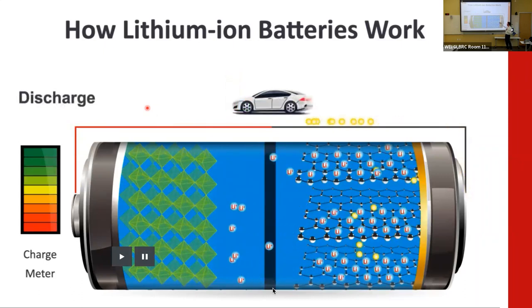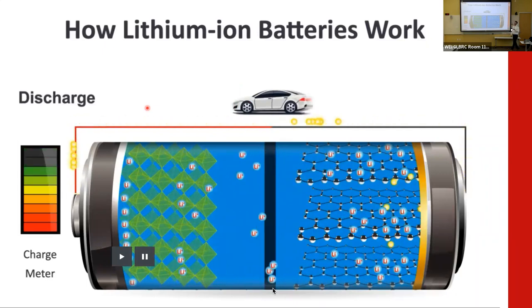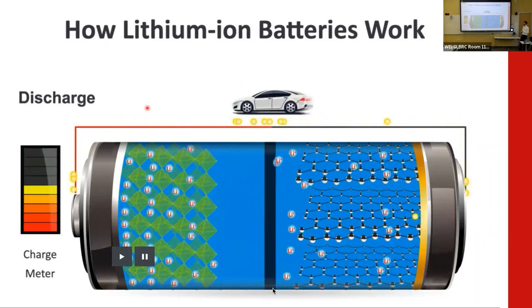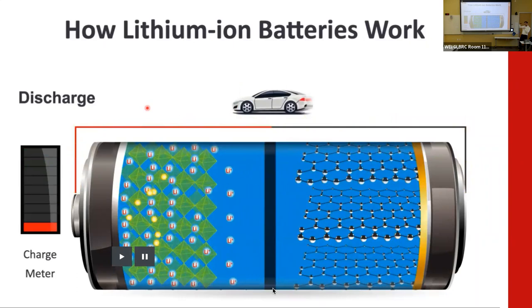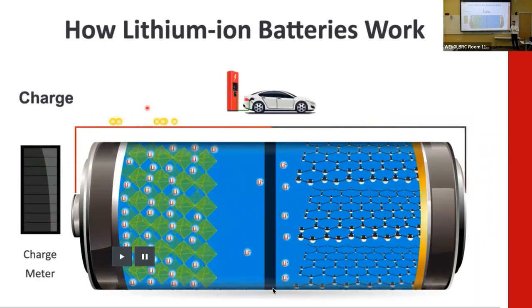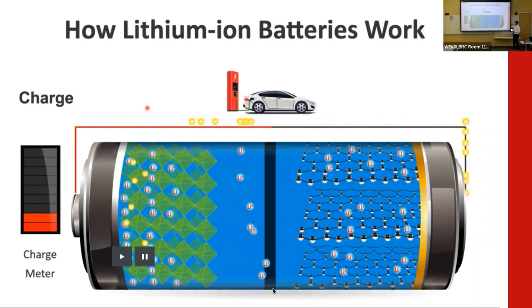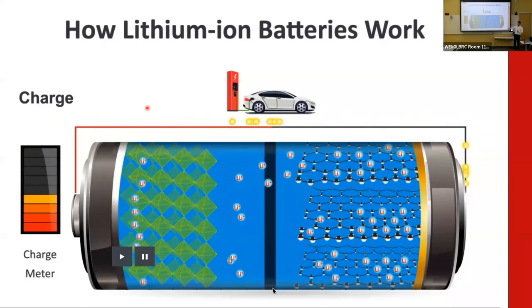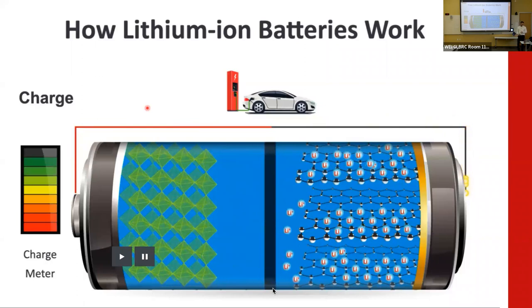Inside of this is graphite, this layered structure. The lithium really doesn't want to be there very much. It's almost in the metallic state. So the voltage of that is different, right? Voltage is a way to think about potential or the energy level. So there's an energy difference between these two sides. And by allowing the ions to then flow back, right?